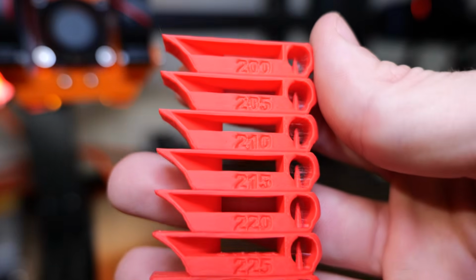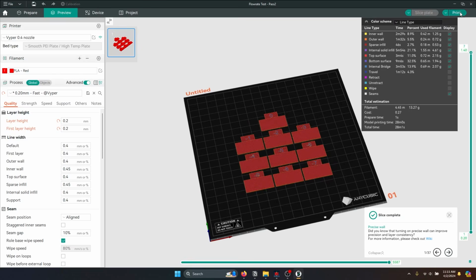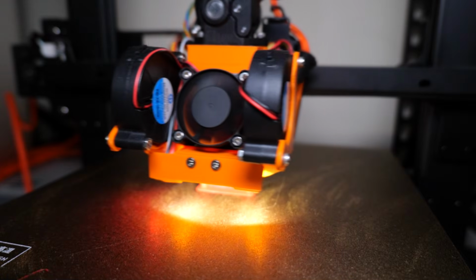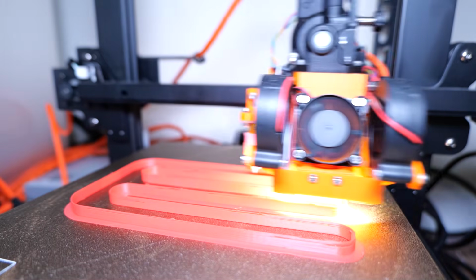Now that the printer was calibrated, I decided to go ahead and retune the filament. I basically did the temperature towers, flow calibration, pressure advance, retraction, all the good stuff. I ended up doing 2 separate profiles, one for 200 Celsius and one for 230 Celsius. The speeds for those profiles were limited by the max volumetric flow, so at 230 Celsius it was about 32 cubic millimeters per second, and then at 200 Celsius it was about 20 cubic millimeters per second. I did this so that I could compare cooling at basically different temperatures and flow rates.